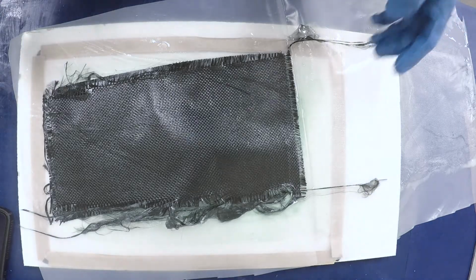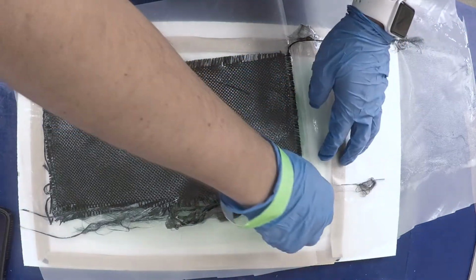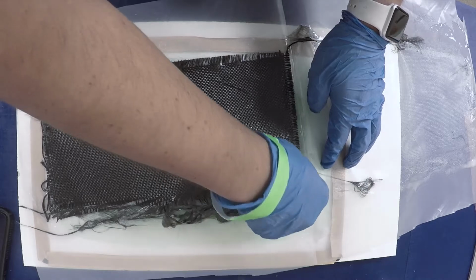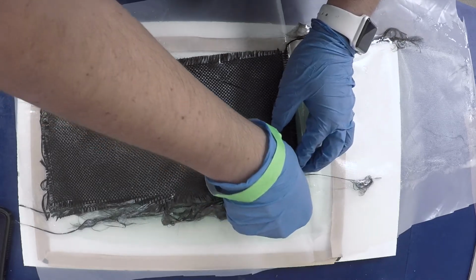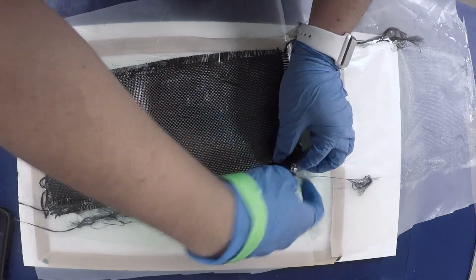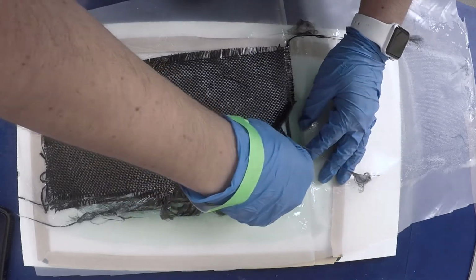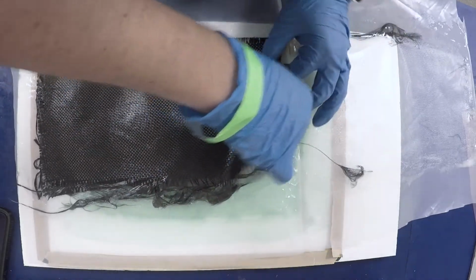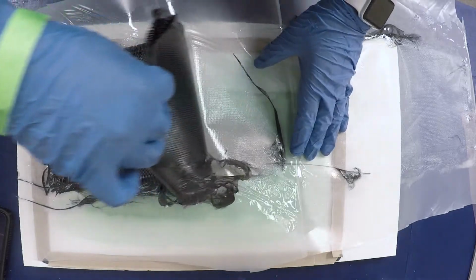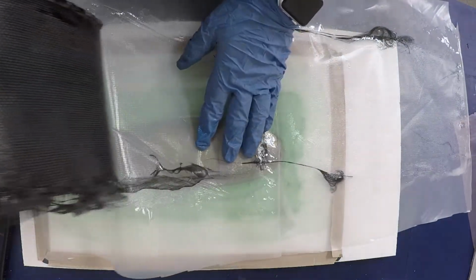Having completed the amount of layers desired, you can remove the wet laminate from the plastic and place it on your mold. As you peel off the laminate from the plastic, be mindful of any loose fibers that can become stuck to the plastic and unweave or distort your laminate. Avoid lifting by just one corner, as this will also distort your laminate.